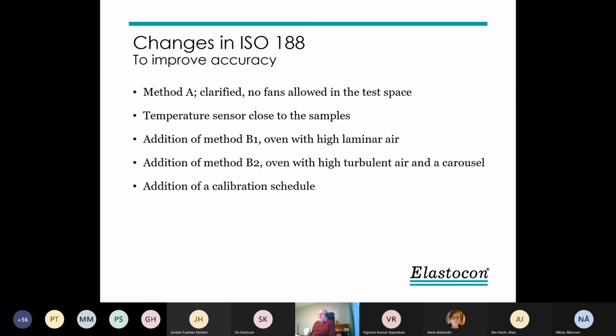Later on, we have in that standard added the method B1, where we instead have a high air speed but laminar speed. And later on, also method B2 with high turbulent air speed and the carousel. The method B2 especially, I may say, might give even better repeatability and reproducibility in one way. But of course, it's not the same results as you get with method A, because you lose more weight and you have a higher oxidation of the surface as well.